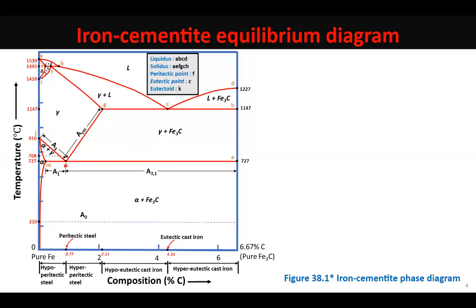And just after the eutectoid reaction, this 100% austenite will undergo the eutectoid reaction, and whatever ferrite and cementite you'll have would be eutectoid ferrite and eutectoid cementite, meaning you'll have 100% pearlite present in this steel. If you look at the steels to the left of it, they do have austenite, but along with that some ferrite is also there. And this ferrite, students, would be called pro-eutectoid ferrite, because there is another ferrite going to be formed when austenite transforms to pearlite.